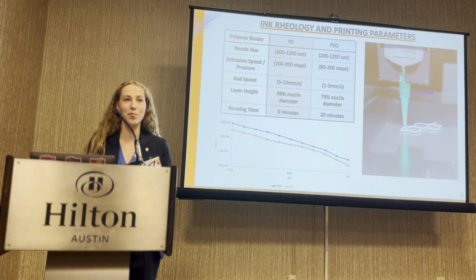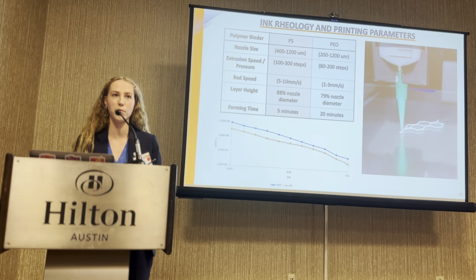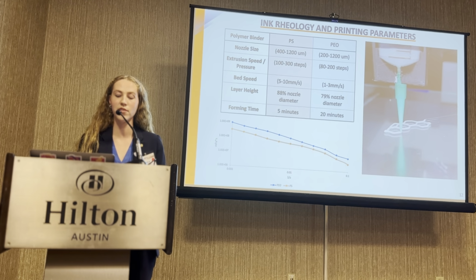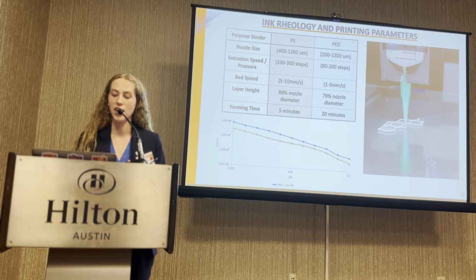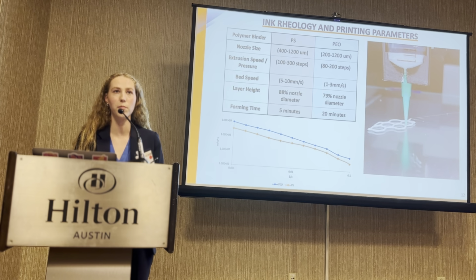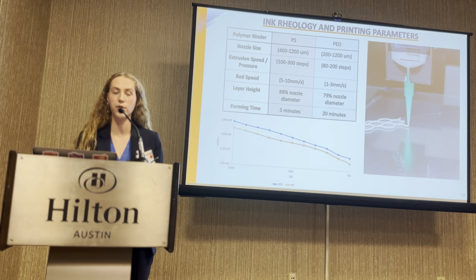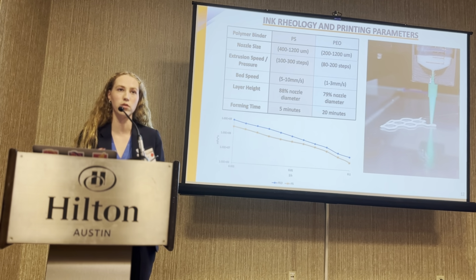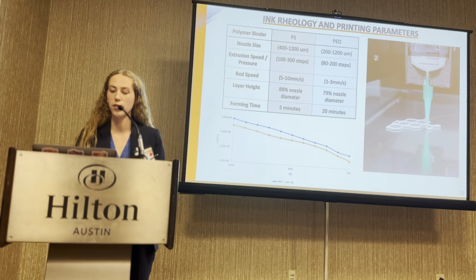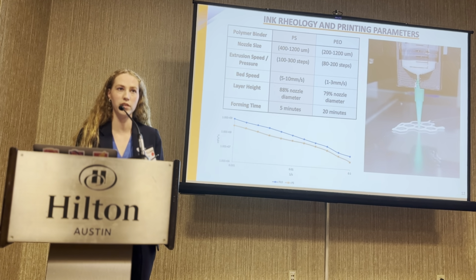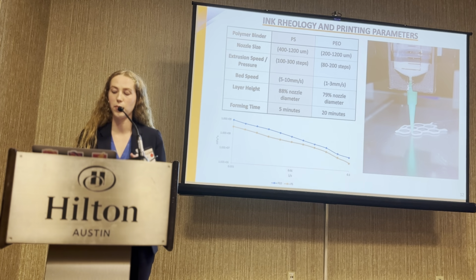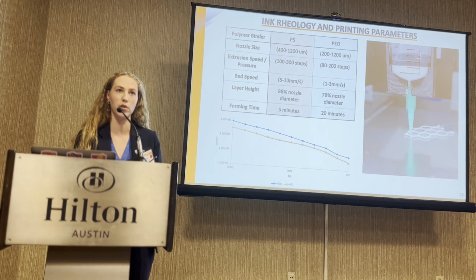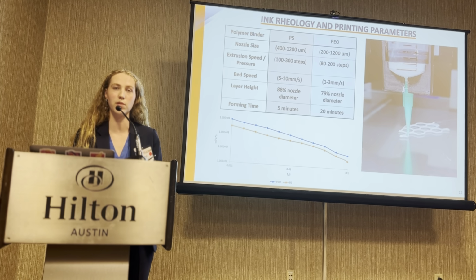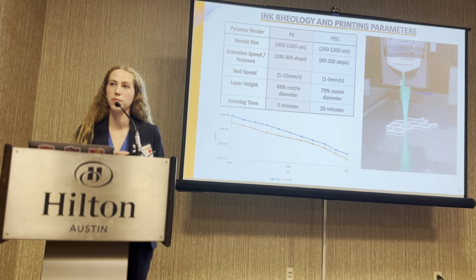Now getting into the printing process, as we went about printing and optimizing the machine settings, we arrived at these in the table here, and our conclusions in general were that the PEO binder is thicker and greater viscosity, which led to it requiring slower printing speeds. However, the post-forming time is one of the most important capabilities, and the polystyrene becomes much more brittle more quickly, so that PEO is much better for shaping post-print.